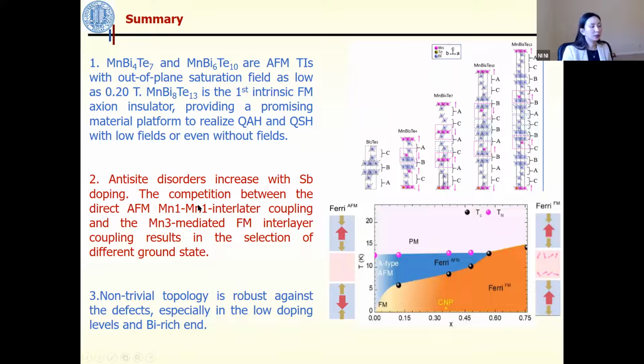And the antisite disorder increases with the antimony doping. As you can see, this kind of antisite disorder can tune the magnetism and the band topology, right? Because of this manganese-mediated ferromagnetic interlayer coupling, we were able to see a rich magnetic phase evolution here. And the topology turns out to be robust against the antisite disorder, especially at low doping levels, and in the intermediate doping levels, we found a possible magnetic Weyl semimetal state here.